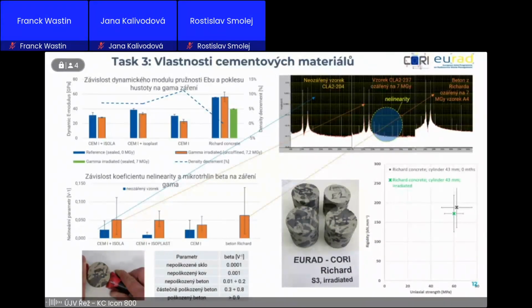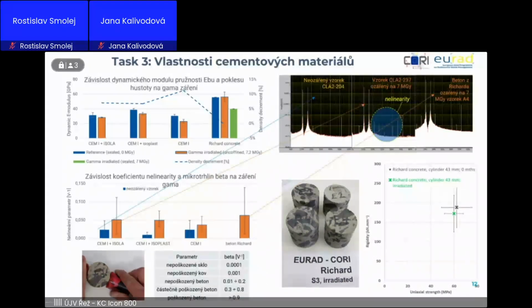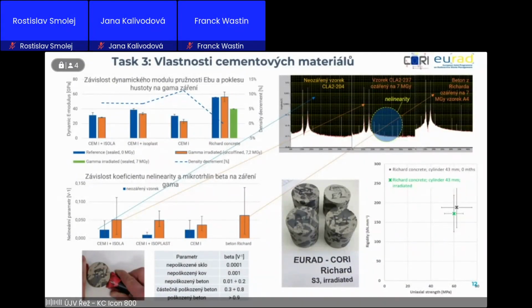On the left-hand side, on the top, there is a simple ultrasonic testing. I send an ultrasonic signal through a sample, measure the time of the transmission, and calculate the modulus of elasticity. You can see that when there is a plastificator, Isola, there's a very small decrement of modulus of elasticity by radiation; with plastificator Isoplast, or when there is no plastificator, there is a higher decrement.